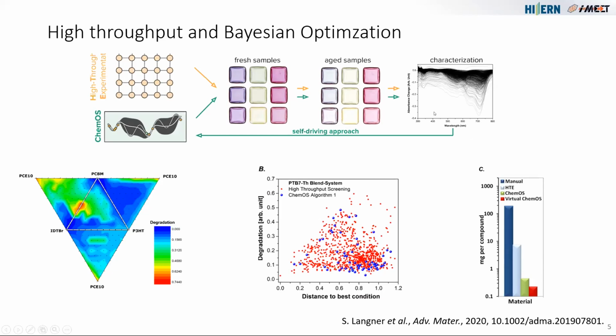And then based on all this data, what we could do is feed this into an algorithm and then predict new combinations that should be more stable. So basically here we are combining this high throughput approach that I've been showing here, which would be all the red dots in this diagram, together with another approach where we're doing these iterated tests of just a few samples, not thousands, but only 9 or 6, getting the results, defining the new experiments, making the samples, evaluating, and going back to sample preparation. And this basic loop where we are mainly using Bayesian optimizers is the thing that we also continue to use later then for solar cells, for processing conditions optimization, and also for composition optimization.